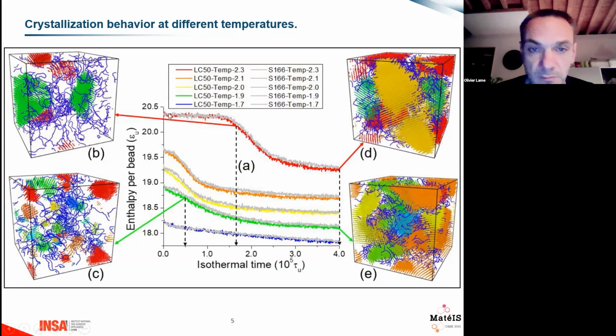For example, here we are at high temperature, and we go from the beginning of the crystallization with some nuclei to the end of crystallization, after waiting, in fact, a long time. Again, this time is not directly comparable to reality, but it finally allows the system to be filled with crystallites. It's the same for a lower isothermal temperature. The only difference is the number of crystallites and also the crystallinity. So these systems are satisfactory because they are realistic compared to what we know about crystallization in real systems.